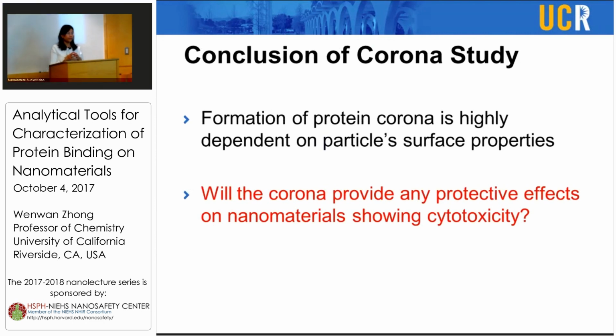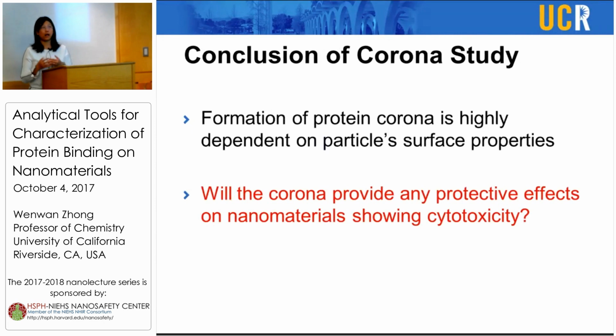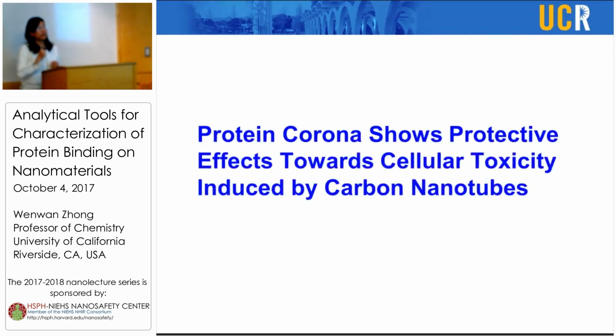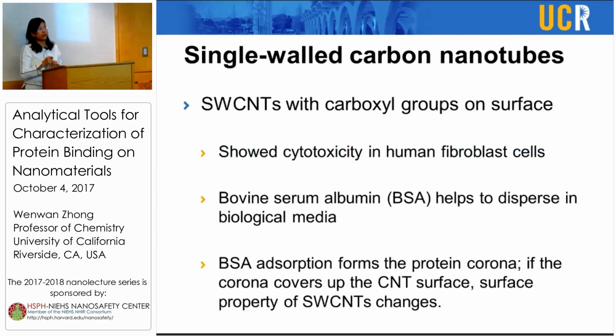Then when we identified the formation of the corona, the next question is whether this corona indeed provides any protective or disruptive effect on the material when they interact with cells, for example. So therefore, we did a quick study of how this protein adsorption could protect the cells from invasion of nanomaterial, which is the carbon nanotubes. So what we did is that we have the single wall carbon nanotube carrying carboxyl group on the surface. This carbon nanotube showed some toxicity towards the human fibroblast cells. But if we coat them with bovine serum albumin, then this toxicity would be decreased or even gone.